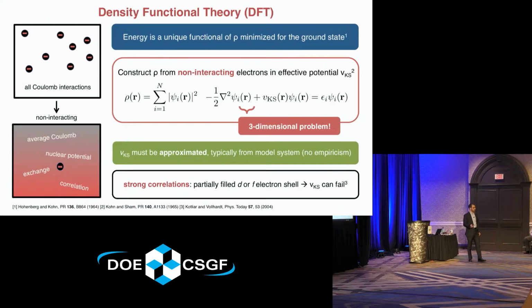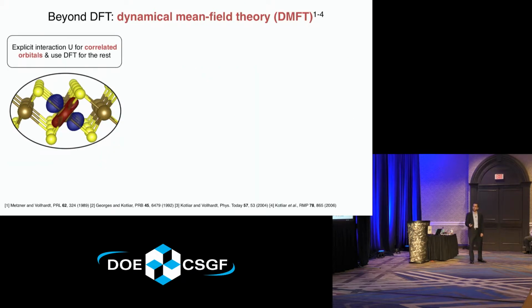So what can we do in these situations in which we have strong electronic correlations? One approach is as follows. You can imagine picking out some subset of the electronic degrees of freedom, namely those localized d or f orbitals. So for example, here's a d orbital on a transition metal site in a crystal. One can include an explicit Coulomb interaction, which we call U, just within this subspace, and then we can just use DFT for the remaining degrees of freedom.